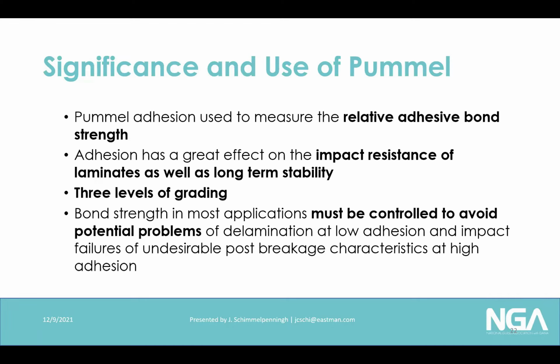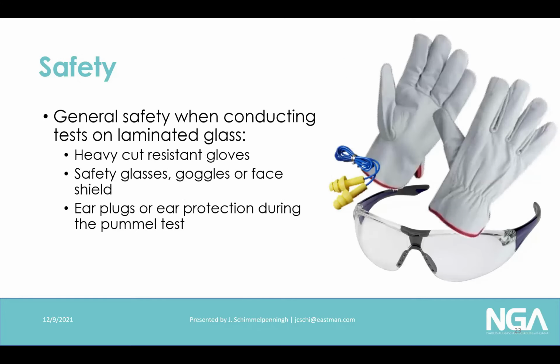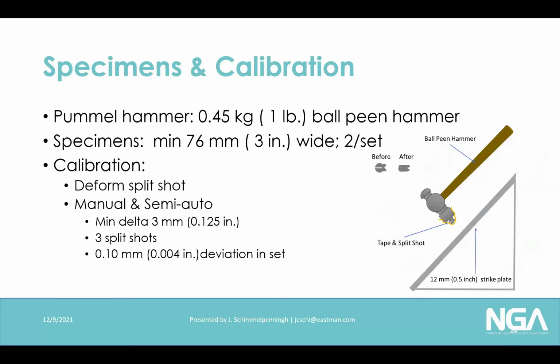Adhesion does have a huge effect on impact resistance as well as long-term stability. There are 3 levels of grading that are in this standard, and bond strength in most applications needs to be controlled, and that is to avoid potential problems of delamination if the adhesion is too low, or sometimes post-breakage characteristics that are undesirable at high adhesion levels. And so you do really want to target it for the type of application you're looking for. Because you are smashing glass, there are some general safety guidelines, cut resistance gloves, safety goggles or glasses, and a face shield, and it does get loud. And so hearing protection is also very highly recommended.